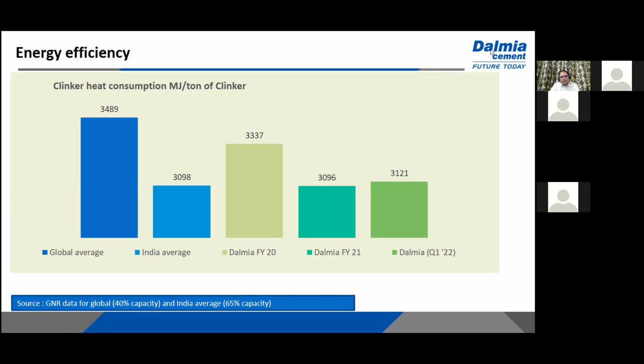And you can see it from the chart which I have shown. There's a significant sizable difference between global average and India average. And we are also working good on energy efficiency. We are taking a lot of measures to reduce our energy consumption. At the same time, when we use alternative fuels, the energy consumption goes up because the alternative fuels or green fuels are not very dense like coal or pet coke. So due to this, there is some loss in the efficiency, but the overall impact is still better because ultimately the waste disposal happens and emission reductions do happen.